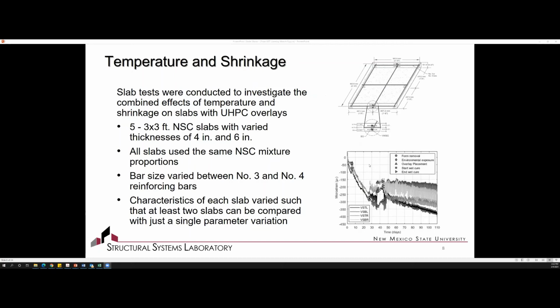These slabs were 3 feet by 3 feet, and they varied in thickness from 4 inches up to 6 inches, also with very different reinforcement ratios. We looked at the various reinforcement ratios and how this affected the behavior. We monitored each of these slabs for over a year, so that we could see the load and temperature cycles. We had vibrating wire strain gauges embedded in these, as well as foil strain gauges on the reinforcement. You can see down here in the corner our time versus microstrain.